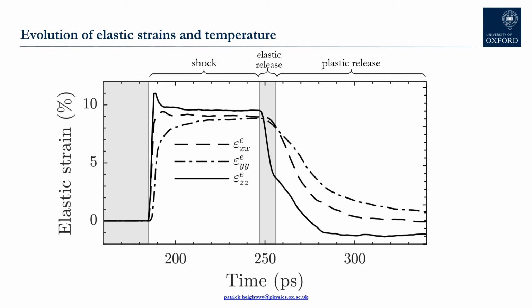From the graph we can see that the release back to ambient pressure actually takes place in 2 phases. There's first a period of elastic release, during which the elastic strain along Z rapidly decreases, but the transverse strains remain constant. But within 5 picoseconds, the shear stresses inside the element have built to such a level that the crystal yields, plastic flow ensues, and that's evinced by the transverse elastic strains decreasing at about the same rate as the longitudinal elastic strain.